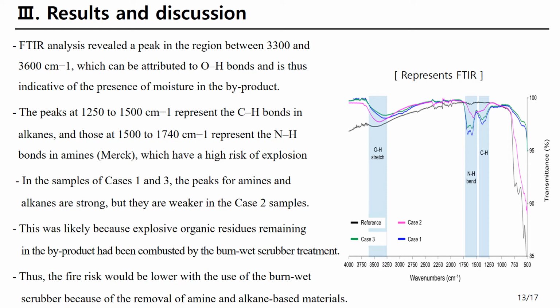In the samples of case 1 and 3, the peaks for amine and alkane are strong, but they are weaker in the case 2 sample. This was likely because explosive organic residue remaining in the byproduct had been combusted by the burn-wet scrubber treatment. Thus, the fire risk would be lower with the use of the burn-wet scrubber because of the removal of amine and alkane-based material.